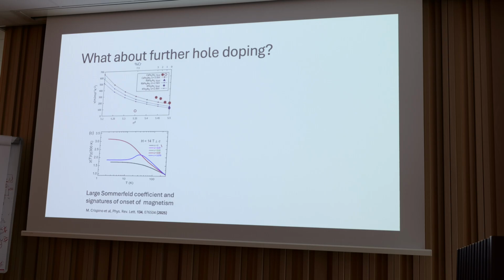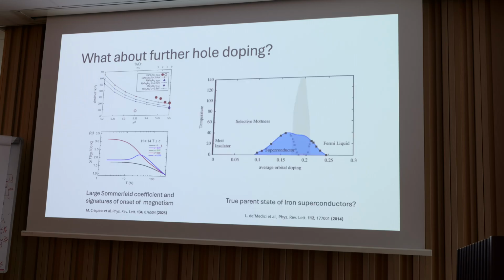So we saw from our own studies that the DXY band is becoming more localized with increased hole doping. They see with further hole doping the system is becoming more localized, and they're seeing these very large Sommerfeld coefficients. And so that leads to the question, which turns out this is a 2014 paper. I thought that I arrived here on my own conclusion, but maybe everyone has had this idea for a while. But you can ask what's the true parent state of the iron superconductors, because we're used to thinking about it from this n=6 filling, but perhaps this Mott insulator is the true parent state, and then you get superconductivity